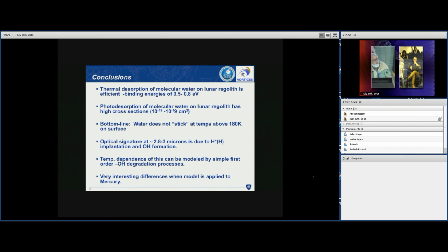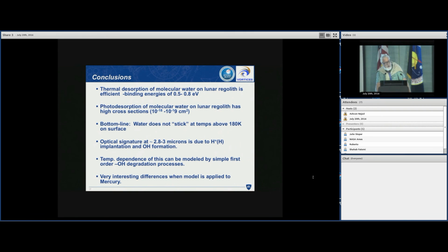So it depends on how deep into the rim you want to look. The hydroxyls that we're looking at are within 2 to 3 layers thick, right? And so they're really superficial. And if you have a really porous material and you're able to get in there, they should be at the surfaces of the pores. Frankly, to be honest, we've never looked at a metal oxide mineral that is not hydroxylated, if you look at the very terminal surface.